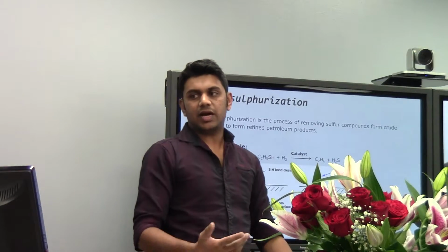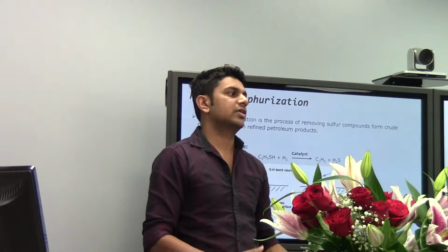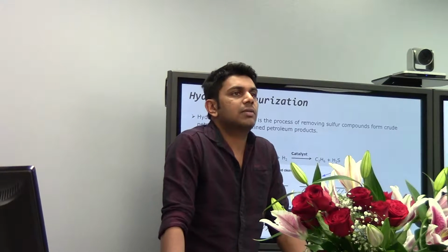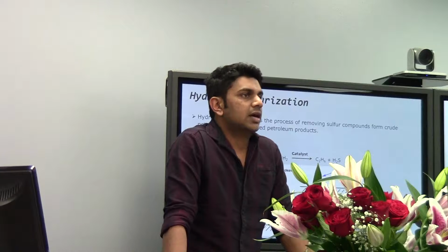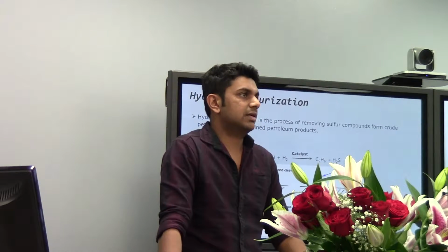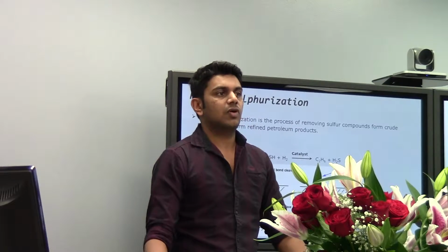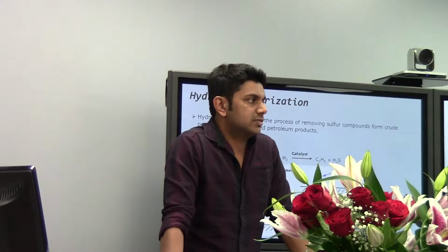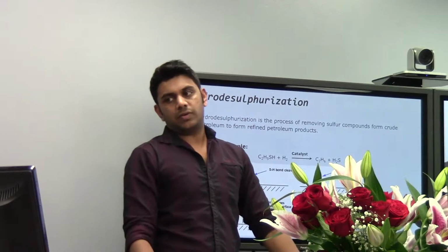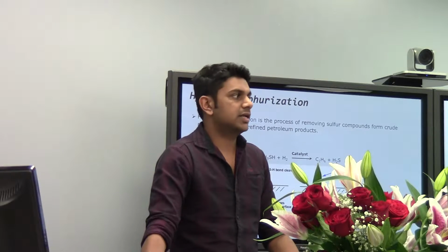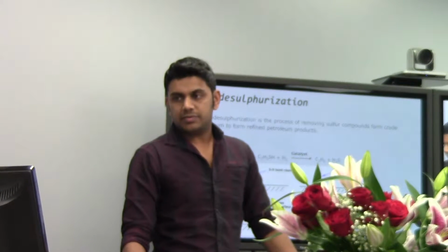During this sulfur removing process, the sulfur-contaminated hydrocarbon is treated with hydrogen gas in the presence of a heterogeneous catalyst at elevated temperatures and pressures to form refined petroleum products, and hydrogen sulfide is formed as a byproduct. Here you can see a simplified catalytic hydrodesulfurization reaction mechanism in this diagram.